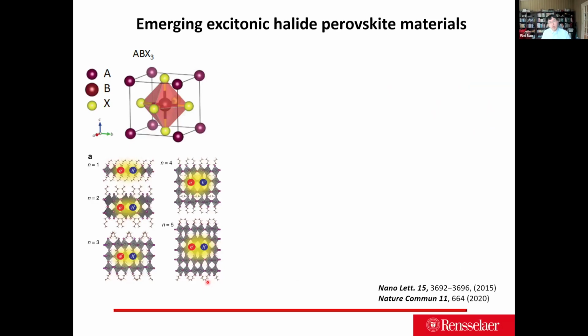Because at that time I was struggling with exciton polaritons, the quick question I asked is whether the material shows a sizable exciton against the thermal fluctuation. The answer is yes, they do show exciton. Plus, it's not a Frenkel exciton, although it's a spin coated material. It's a Wannier mode exciton. So essentially, the exciton exists in the octahedral of this ABX3 halide perovskite structure. The inorganic part is typically in the octahedral structure, and this exciton mainly resides in the octahedral structure in the perovskite.